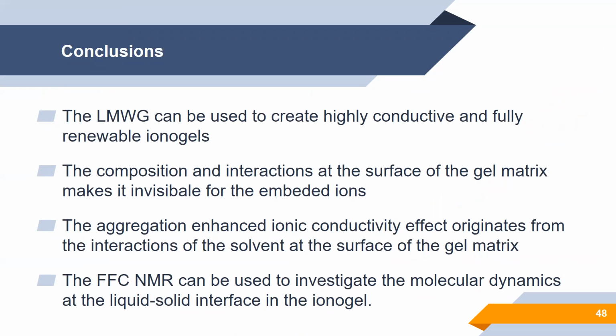Okay, so going to conclusions. I would like to say that the Ionogels are interesting materials worth being studied as they allow us to create systems which are highly conductive, which display an enhanced conductivity effect that can actually be used to monitor the internal structure of the gel itself. These materials are thermoreversible, so we can use them and prolong their lifetime if it is necessary. Because of the water or solvent molecules adsorbed at the surface of the gel matrix, this matrix becomes invisible to ions and they can move more freely.